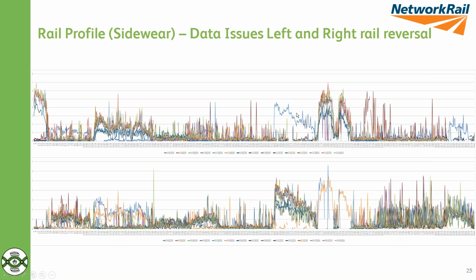These different colours are all different runs on different dates. Ideally we would see it changing from run to run as sidewear increased. But you can see, for instance, the blue bit there, that's very clear in the top trace, that should have been on the other rail. But for whatever reason, on one of the runs, left and right rail were reversed. Where that happens a few times, it starts to give you quite misleading information. So I'm trying to say it's key that we get data accurately positioned and accurately reported, if we're to make better use of the system, so people get to trust this information and rely on it as a means of identifying problems or at-risk locations. So yes, some challenges there with how we make sure that's always consistent, but very clear in the sidewear where we have reversal of left and right.